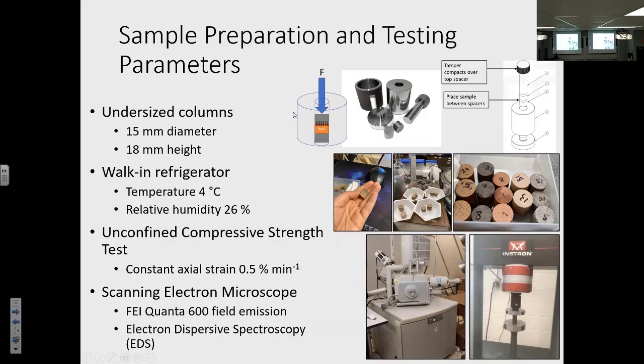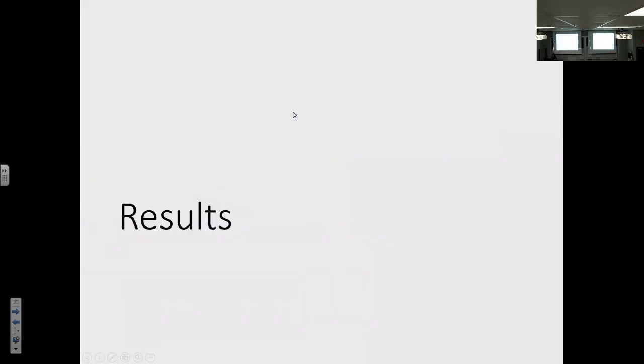And then after it breaks, I collect whatever little pieces are left, and then I sieve them. I try to get the finest particles I can, and then we look at these particles under the scanning electron microscope in order to see any morphological differences. And so for this, we use the FEI Quanta 600 field emission SEM at MIC, and it has an electron dispersive spectroscopy capacity as well. Let's move on straight into the results.